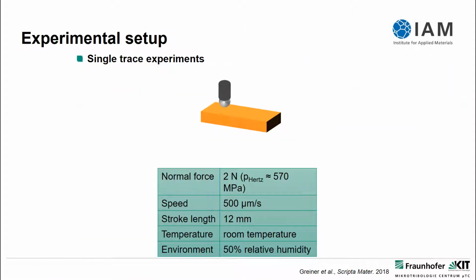So that is our model system that we have chosen. It's a copper plate, using high purity copper, either OFE or OFHC copper—oxygen-free high conductivity copper, with OFE copper being even a bit purer—in contact with a sapphire sphere.